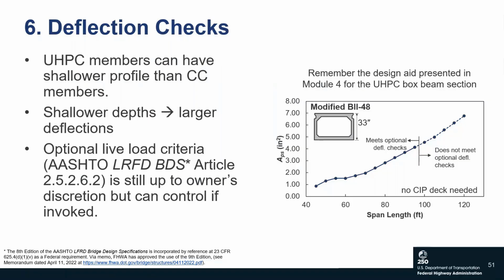And you can see that, because you have a shallow section, your deflections do control after a certain point. So again, you can use the actual UHPC material properties, which are typically stiffer than calculated, and that'll allow for longer spans while meeting deflection criteria. Or you can use transformed section properties, and that can allow you to get those live load deflection limits to